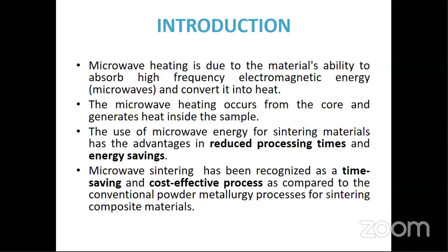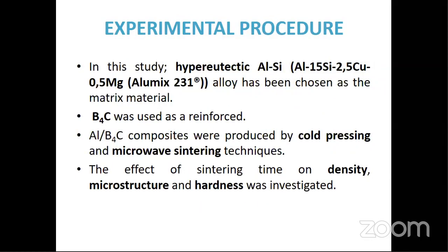The use of microwave energy for sintering materials has the advantages of reduced processing times and energy saving. Microwave sintering has been recognized as a time-saving and cost-effective process as compared to the conventional powder metallurgy processes for sintering composite materials. In this study, hypereutectic aluminum silicon alloy has been chosen as the matrix material. Boron carbide was used as a reinforcement. Aluminum boron carbide composites were produced by cold pressing and microwave sintering techniques. The effects of sintering time on density, microstructure, and hardness were investigated.